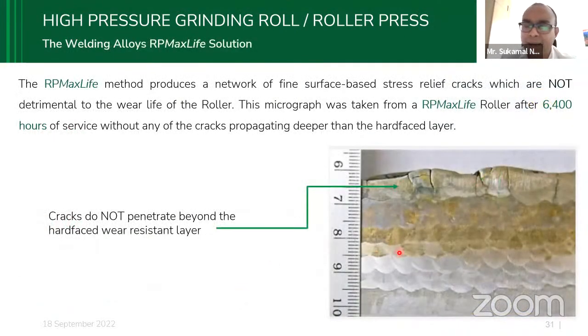This is an interesting product. Actually, it's one of our patented products. You can see that it's very hard. It is showing a crack, and that's not an issue because it shows how hard it is. But the beauty is that this particular crack is restricted here. It does not penetrate inside the material, even after 6,400 working hours.